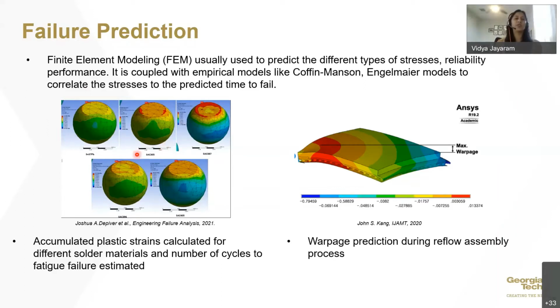It can be used to model different thermomechanical stresses, bake, HAST induced stresses, but it can also be used to model process level information, like how much warpage we would expect based on the CTE mismatch, etc. So typically it is coupled with empirical models like Coffin-Manson and Engelmaier, to name a few, to correlate how the stresses can be translated into the predicted time to fail.